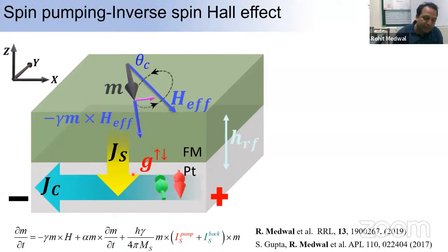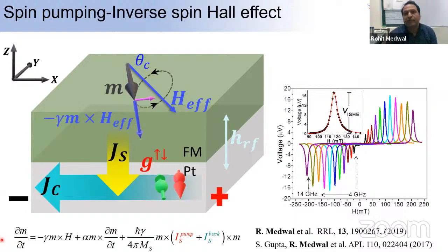And we can use the inverse spin Hall effect, which I explained, to convert this spin current into a charge current. This charge current will generate a voltage across the platinum, and we can measure it. This is the voltage which is generally measured, in the range of microvolts. The interesting aspect here is, how do we know that this is a pure spin voltage, a voltage generated because of the spin motive force?